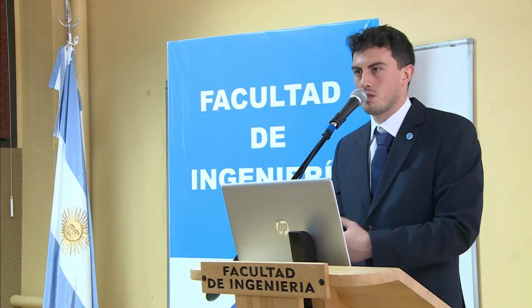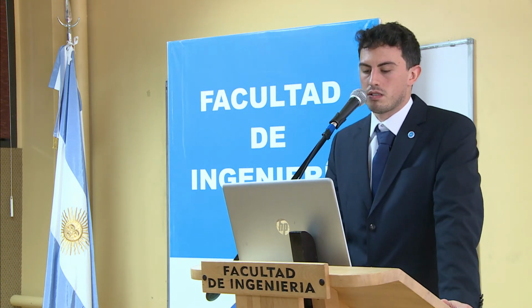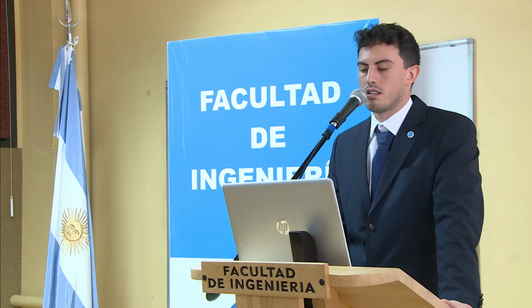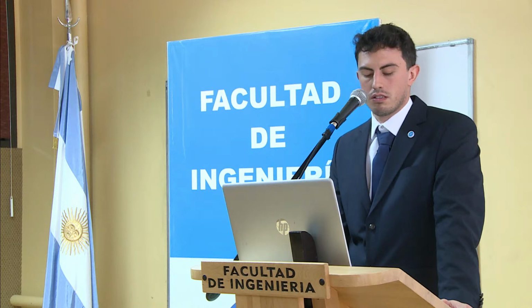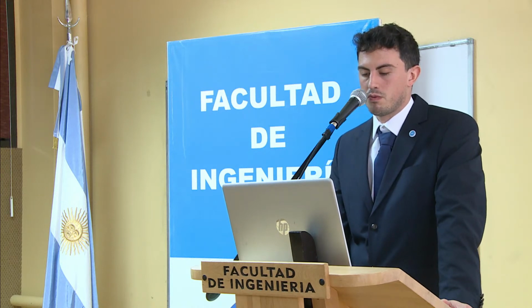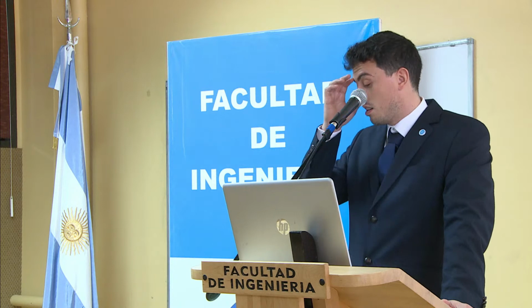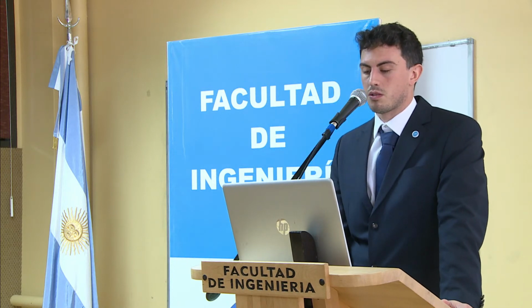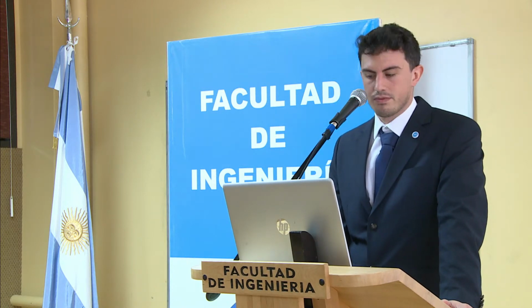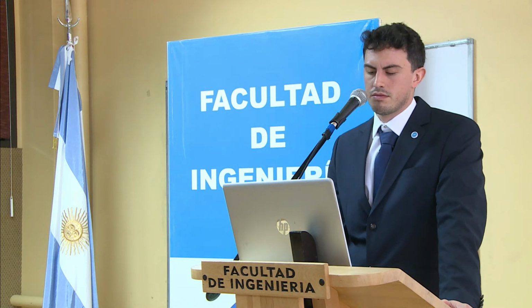The simulation was matching the experimental result as well, and it is interesting because the elastic model in this case was not fitted. It was calculated by the model, and we only fitted the strength, and it's similar to the experimental one. The experimental is the unconfined compressive strength? Yes.